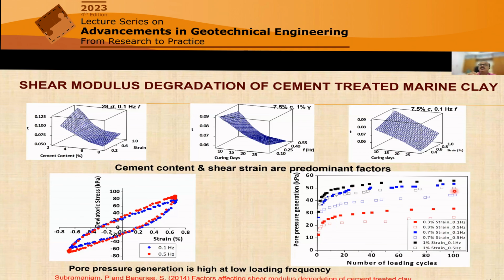The reason being that at the lower frequency, the sample is sustaining the load for a longer duration. So it is slowly going down and slowly going up. The sample under ambient condition is experiencing the load for a longer duration compared to higher frequency loading. So that's one of the hypotheses we made from this analysis, which is very important. In fact, this has direct application in liquefaction. People have already commented that under low to medium frequency earthquakes, the chances of liquefaction are more because the development of pore pressure is more. So it's similar to that type of logic.